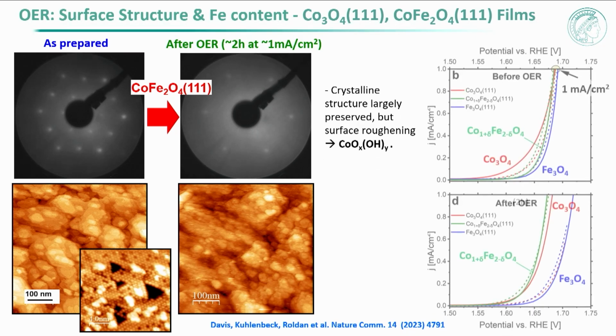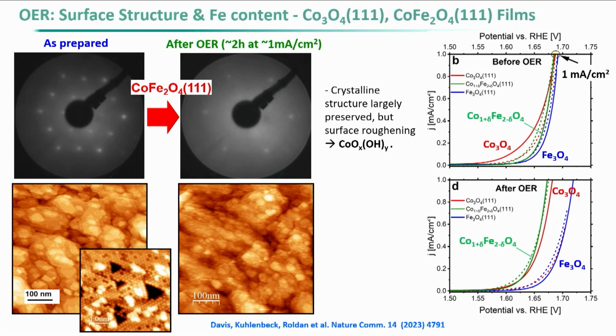So when we are looking at these systems, we can look at our initial material and compare pure iron oxide, pure cobalt oxide, and this cobalt iron oxide. And at the beginning, the cobalt oxide was better than the other two. But if you run the reaction a couple of times, because of these changes that I mentioned before, the catalyst is dynamic, then it turns out that the best catalyst tends to be lower overpotential, tends to be the one that includes a little bit of iron.